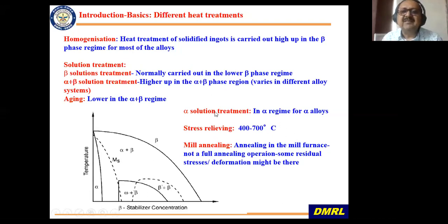Then you have in alpha alloys what is known as alpha solution treatment, which is in this region. For these kinds of alloys, you basically solution treat here. So it can both relieve the stresses as well as solution treat. And there is also stress relieving that we normally do, especially in welding and all. And mostly the temperature regime is 400 to 700 degrees centigrade, and it is mostly in the alpha plus beta regime. It is normally not done above the beta unless there is some requirement.